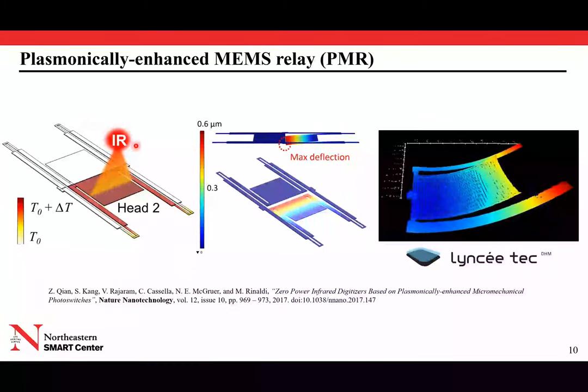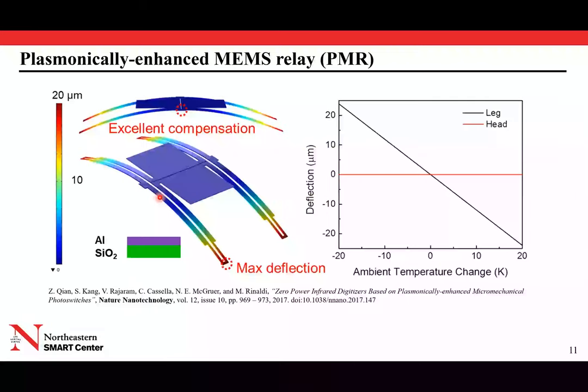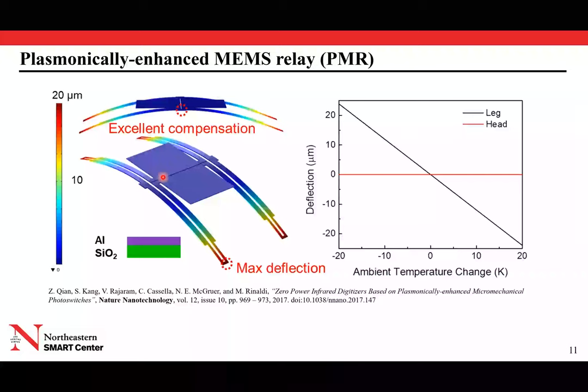So the working principle is that when the device is exposed to infrared radiation that matches the wavelength defined by that absorber, the radiation is absorbed by the head, and the temperature of this structure increases up to these thermally insulating regions, right? Since the temperature of this inner pair of thermally sensitive legs increases, that causes downward bending and vertical displacement of the contact tip. So the device is very sensitive to impinging infrared radiation in that wavelength or band of interest. On the other side, the device is pretty much immune to all the common mode inputs that we might have in there. It could be, for example, ambient temperature variation or residual stress in the thin film materials that we use to build this structure.